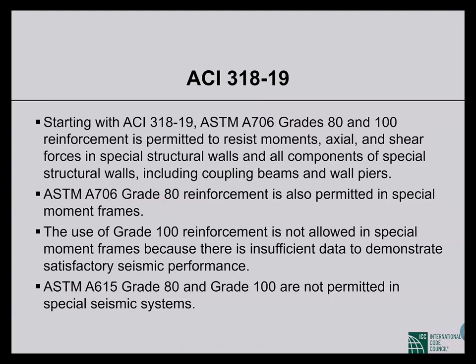In special moment frames, grade 100 is not permitted, but grade 80 of ASTM A706 is permitted. The use of grade 100 reinforcement is not allowed in special moment frames because there is insufficient data to demonstrate its performance, so that is not permitted. ASTM A615 grade 80 and grade 100 are not permitted in special seismic systems. That is okay. In our case too, we don't permit grade 80 and grade 100 produced according to ASTM A615. But grade 80 is permitted according to ACI 318-19.